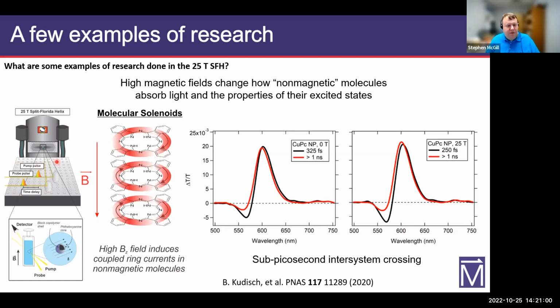So this was an ultra-fast pump probe measurement. It was a broadband transient absorption measurement. We're looking at the transient transmission of the probe over a range of wavelengths. And you can see here the time-resolved dynamics of these porphyrin molecules. And there are delocalized electron pi states. And when you turn on a magnetic field along the axis of these molecules, the field changes the intersystem crossing dynamics. So here it is at 0 Tesla,